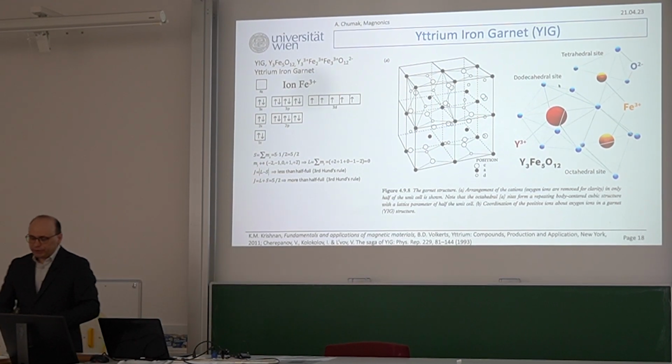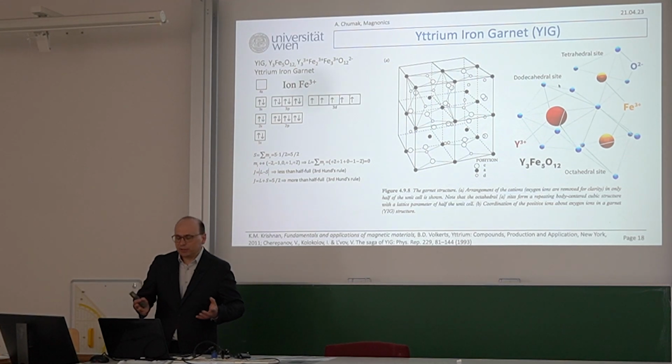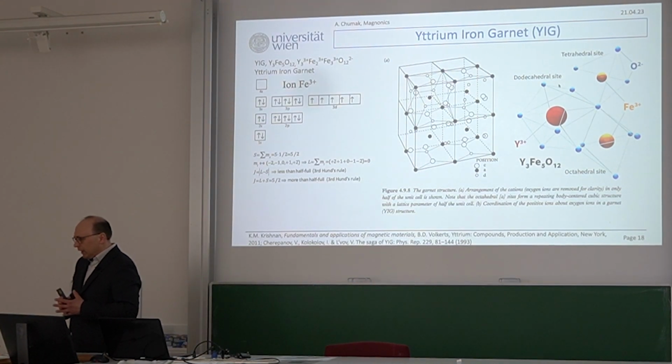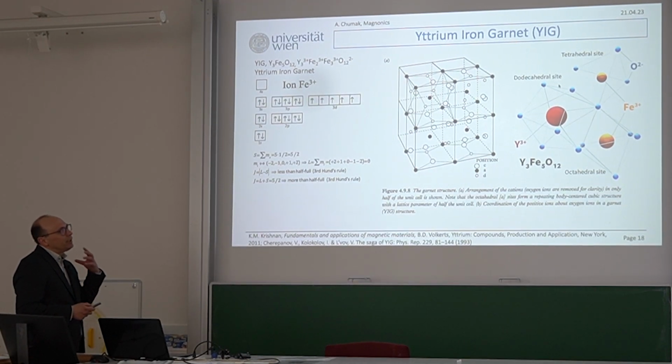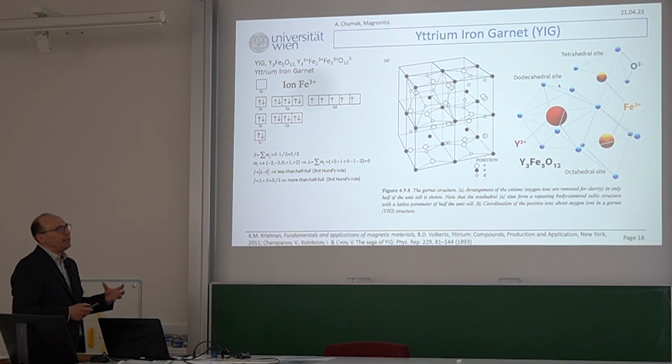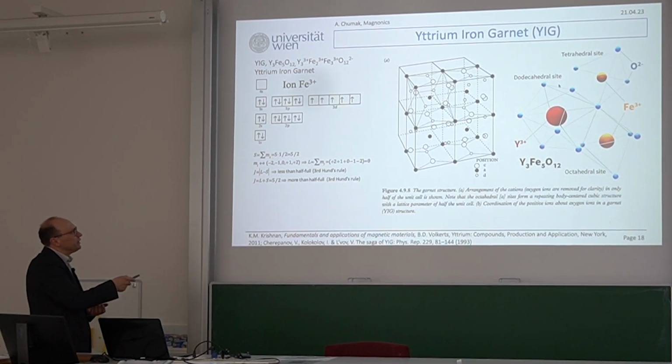And this is particularly the reason why spin-orbit interaction is suppressed. I would not say that it doesn't exist in reality, because otherwise we would have no damping probably. But it's a very small spin-orbit interaction, and as a result, the coupling of the spin system to vibrations of the lattice is small, and as a result, damping is small, simply because L equals 0. Then you need the third Hund's rule just to calculate the total angular momentum, but since L is equal to 0, it's easy. It will be simply equal to S.